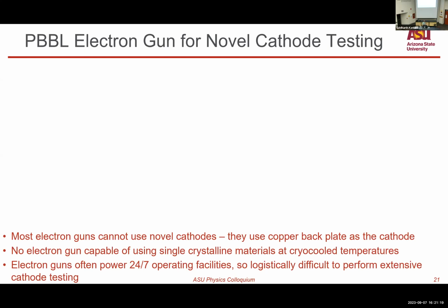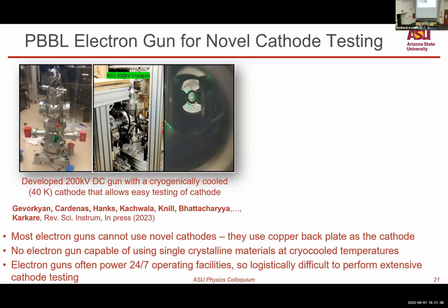And those electron guns that can use some sort of novel cathodes are often used to power 24/7 operating facilities like colliders or XFELs, and it's logistically very hard to perform extensive cathode testing at these guns. So we developed our own electron gun where we can do that. It's a 200 kilovolt DC electron gun where you can cryogenically cool the cathode to 40 Kelvin. It's a very hard thing to do, have something at 200 kilovolts, at the same time cool it to cryogenic temperatures. It's a very interesting mechanical engineering problem.